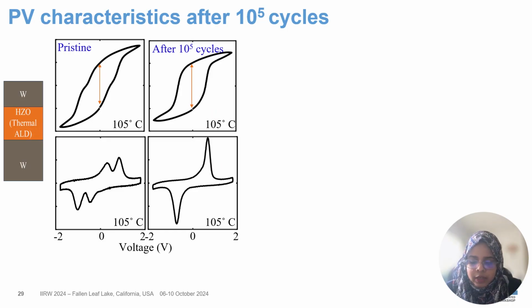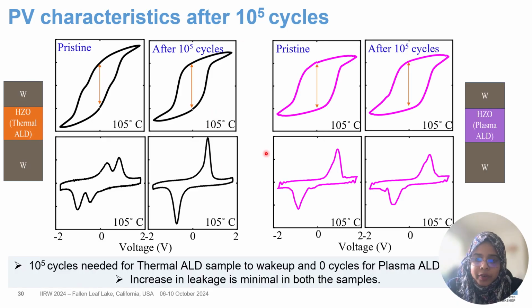Now you have already seen that the plasma ALD devices don't need any wake-up cycles. So this is the PV loop and IV characteristics at pristine state, and this is after 10^5 cycles. So we see a reduction in 2Pr, but we don't see any wake-up effect after 10^5 cycles.